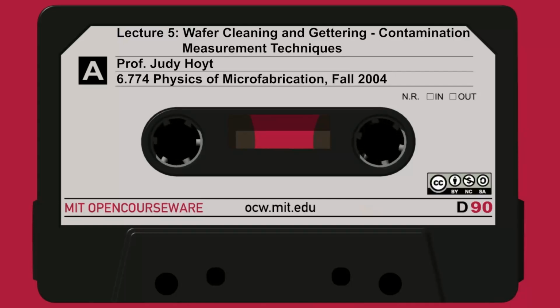Finally, if you go down to this column for the low standby power device, it has an even thicker oxide. So on the same chip, you might have a 2 nanometer, or 2.1, 21 angstrom oxide, and the leakage current through the gate is much lower for this device, about 3 picoamps per micron. So 3 orders of magnitude lower than for the other device, and 5 orders of magnitude lower than for this. So quite a bit different on the same chip. This is the solution people are coming up with. Only the fastest devices have to have the very thinnest oxides. Nevertheless, in a couple of years, we will be hitting the red brick wall. So there's a lot of work to be done on alternative gate insulators.